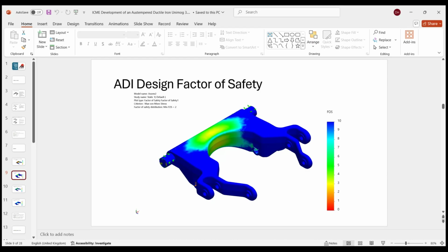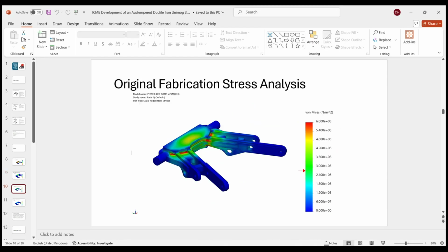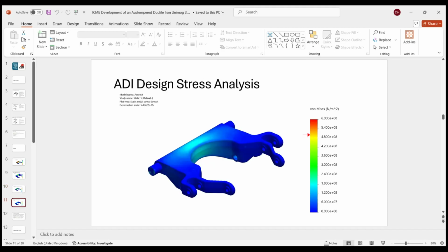And then we look at the stresses involved in the casting and the welded fabrication. So again, we look at the welded fabrication and we have stress values here on average around about 300 megapascals. Some of the welds would be up at 600. So some very high stresses at the welds themselves. And of course, if we're looking at 11 parts, we're looking at a lot of welds. So we're looking at a lot of places where cracks could initiate and failure could occur. Whereas if we look at the ADI version, we can see very, very low stresses.